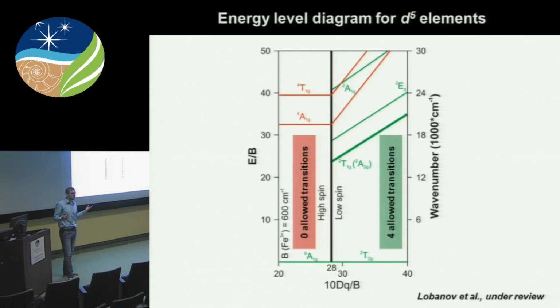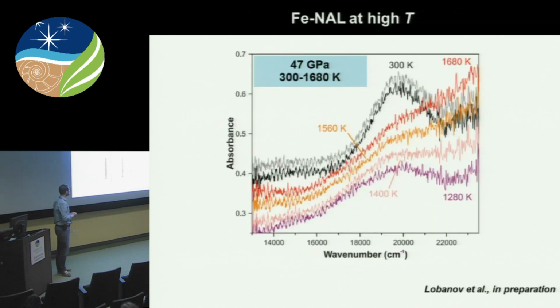You can also ask me now, why do we expect to see a new absorption band that appears out of the blue in low spin NAL, in low spin Fe3+? And really the reason is because Fe3+ has a very unique electronic structure, such that high spin Fe3+ has 5 d electrons that are spread among 5 d orbitals. So there is no way you can excite one electron from one of the d orbitals to another d orbital, preserving the multiplicity, which basically means that there are no allowed absorption bands. But once you squeeze it into the low spin state, you mess up the electronic structure and you get an allowed excited state. So in other words, the appearance of an absorption band is exactly what you would expect for low spin Fe3+.